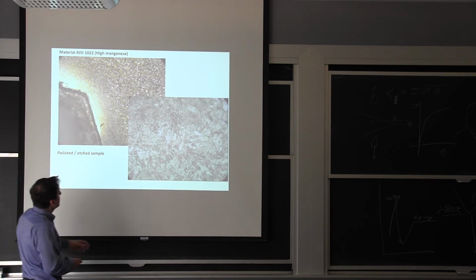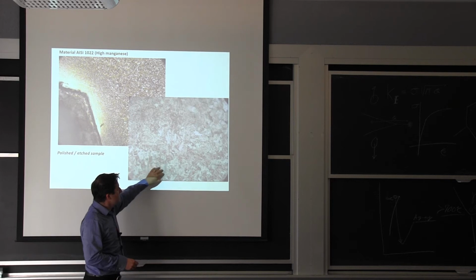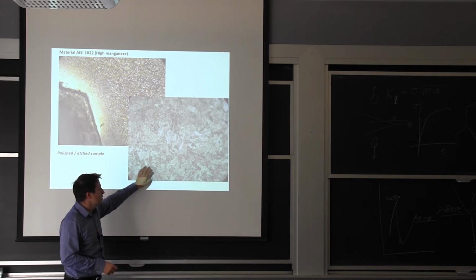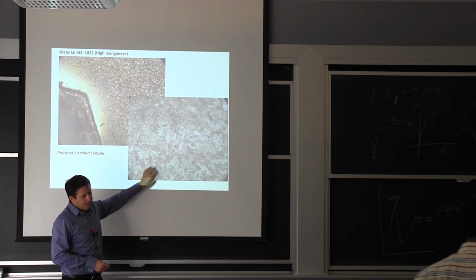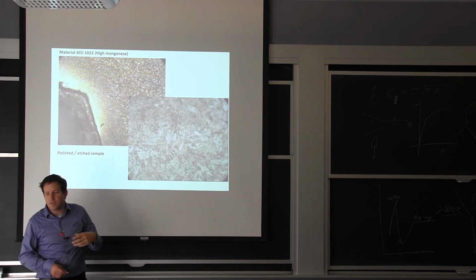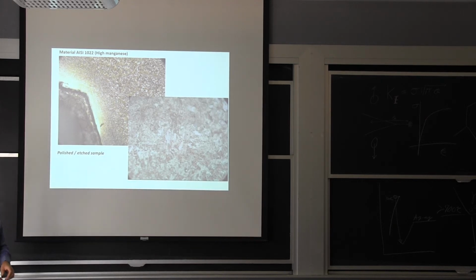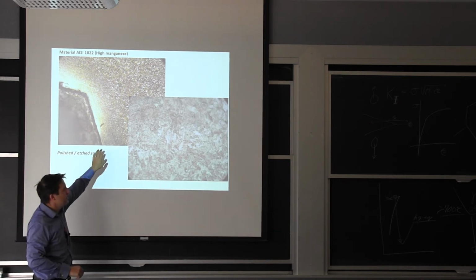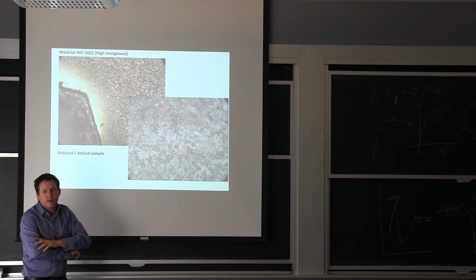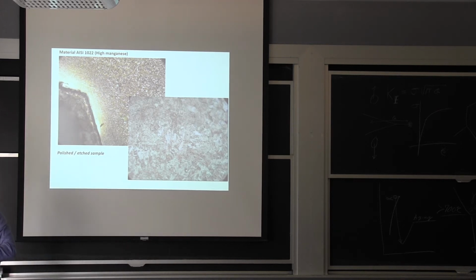When you go to the core, it's a fairly different microstructure. This was quench and tempered. So they went through this series of processes essentially to make this microstructure. So this one was also tempered. It wasn't a 65 hardness on the surface. It was less than that. Where we had 65 was on the tip itself, the part that you see in the self-drilling part. So they had to do a preferential aging of just the structural component of it.